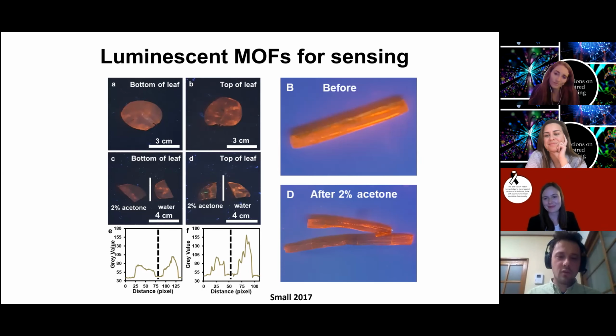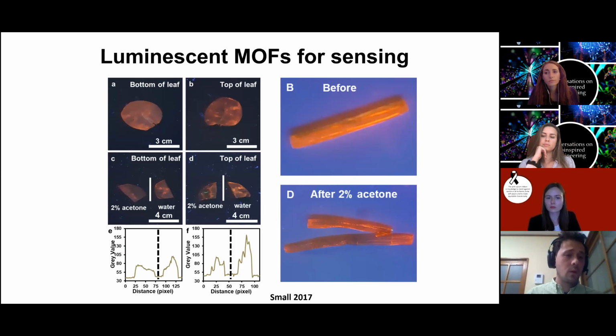But we saw that we could truly, with this, integrate functional material with a functional organism, a plant. This was all destructive, where we were cutting a plant, essentially killing it to do our experiments. But we also did experiments with the roots intact, where we essentially picked out a weed, washed all the soil off, and then incubated it in our two-step process. And we could also get the fluorescence throughout the plant and keep the plant truly alive, where it could propagate.